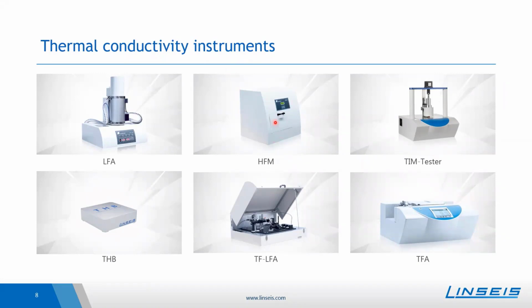The heat flow meter and the TIM tester we offer belong to the steady state methods and are using a plate method where you have two plates which apply the temperature gradient to the sample. These both are for lower conductive materials, the heat flow meter especially for building and insulation materials, whereas the laser flash and the THB are for a broad thermal conductivity range.